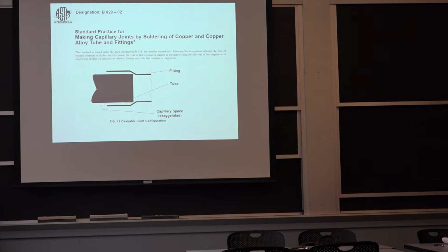Let's make sure, yep. So the two pieces fit this way. It's just about 1/3 of the full circumference here that we're looking at. That was essentially flattened up and pulled apart. And what you'll see is the solder material that was fused and essentially inserted in the joint by capillarity. And there will be a few spots where it's shiny.